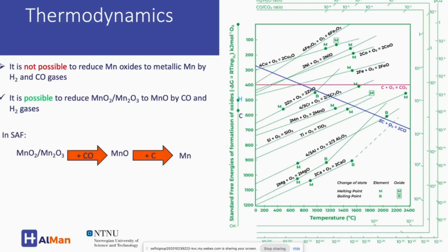Yes, in SAF technology, what we do is actually conversion of manganese oxide to MnO by CO gas in the furnace in SAF. And then down in the furnace, we continue with reduction using carbon and we produce manganese.